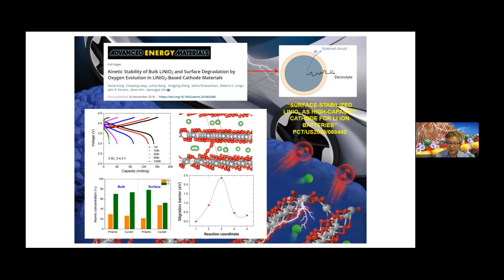And the organic liquid electrolyte is a hydrocarbon. So inside the battery, now you have oxygen, heat, and fuel. When your battery management is not fully operating, at some point they may end up starting the combustion reaction, the thermal runaway reaction, without needing anything else, because just inside the battery has all the ingredients to initiate that spontaneous fire. That's how lithium-ion battery fire happens.